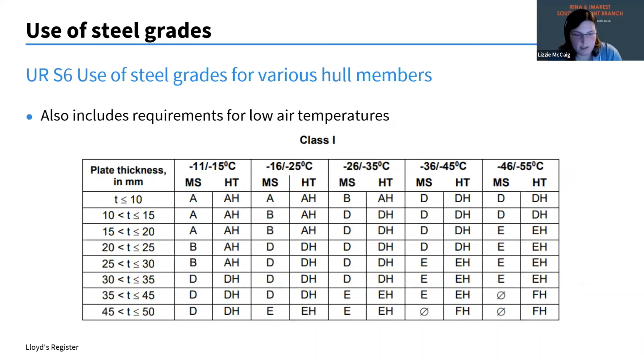If you remember, I said that one of the leading causes of brittle fracture is if the steel's exposed to very low air temperature. IACS introduced this basic table after MV Lake Carling. It was imposed on them by Transport Canada that they had to sort this out. Here you can see that the lower the air temperature gets and the thicker the steel gets, the tougher the material gets, the higher the grade.